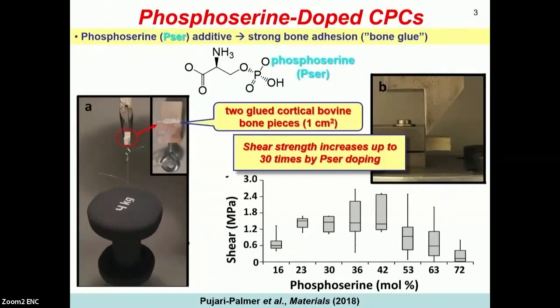And now our co-workers at Uppsala have found that if you mix phosphoserine into the cement formulation, then you get a cement that is strongly bone adhesive. So one obvious application for these materials is to glue fractured bone together. Here you get a feeling of the strength of this glue. These are two pieces of cortical bone that are glued together. Each is only of area 1 square centimeter, but as you can see, this can withstand a load of 4 kilo.